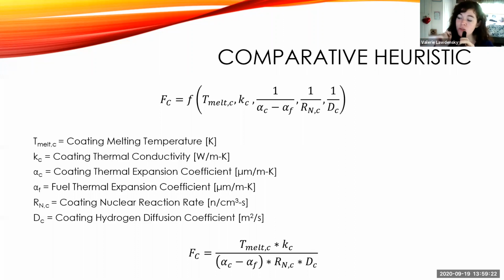But also the hydrogen diffusion coefficient. Now, this is not a common parameter because it's purely experimental and it's based on a lot of things, but it is between the two materials. For example, hydrogen going through zirconium carbide has its own diffusion coefficient compared to hydrogen going through niobium carbide. Hydrogen loves to wiggle into spaces, and at certain temperatures more than others, at certain velocities more than others. It's very, very dependent on the situation. But I was able to find some diffusion coefficients for a few of the materials with the hydrogen. And ultimately, this is the parameter we set up to be able to compare.